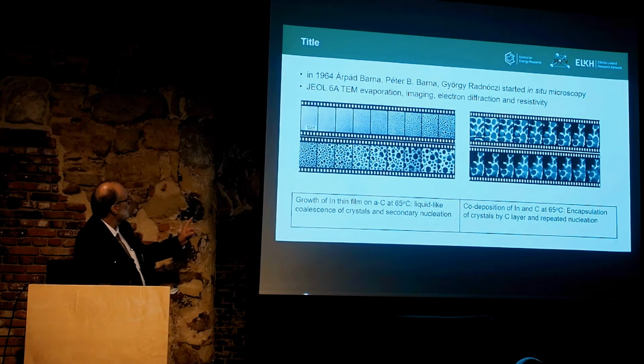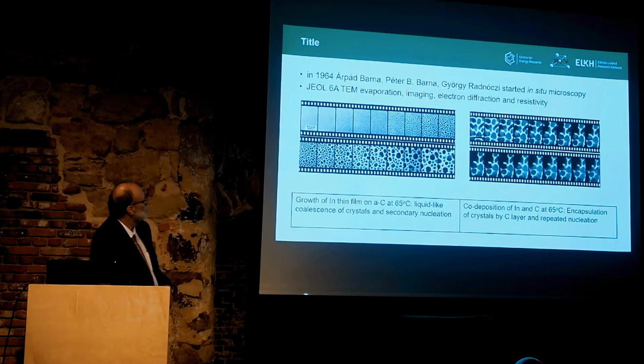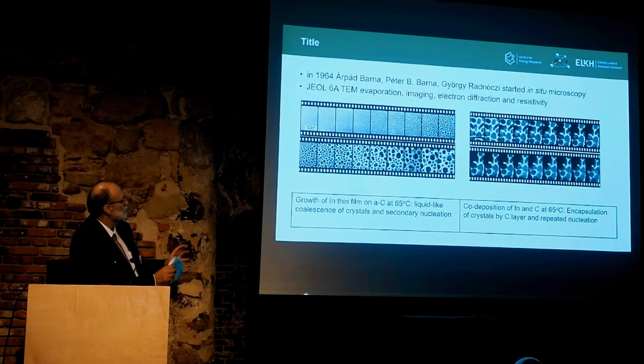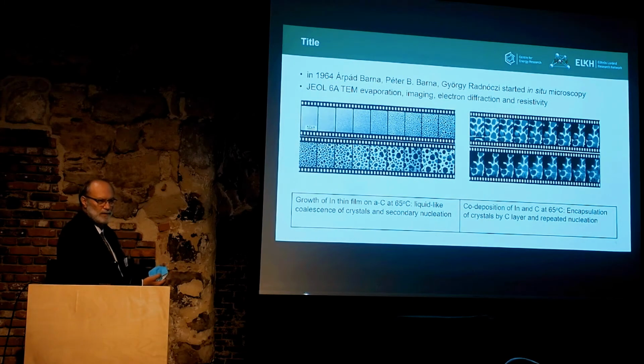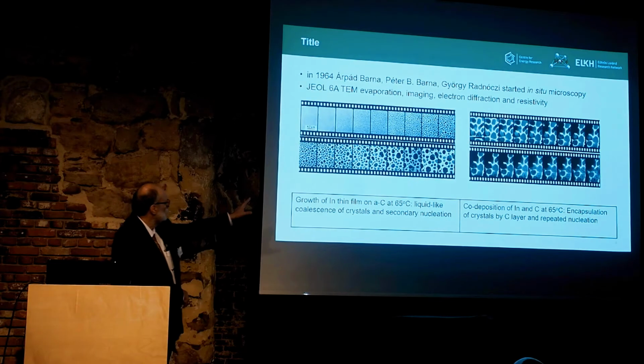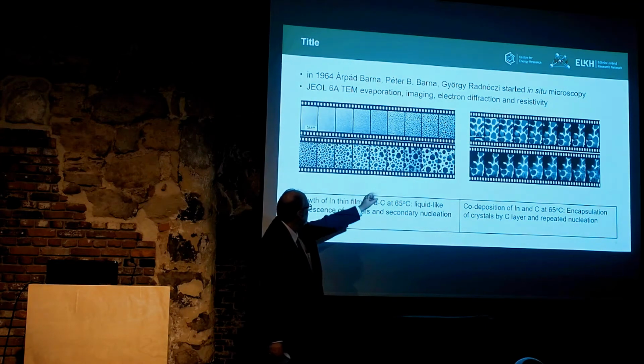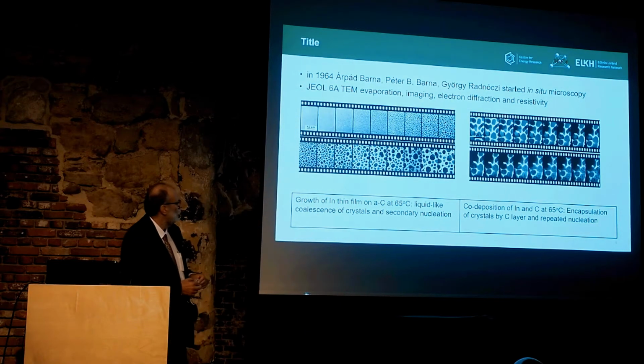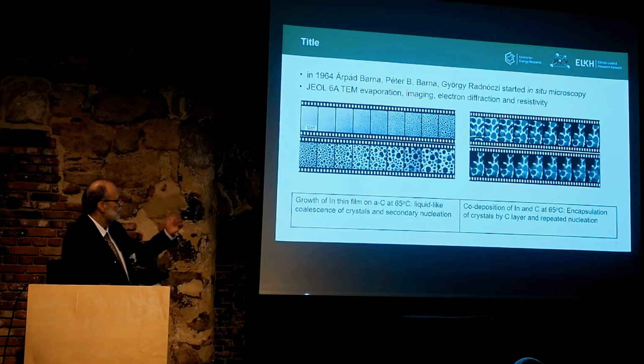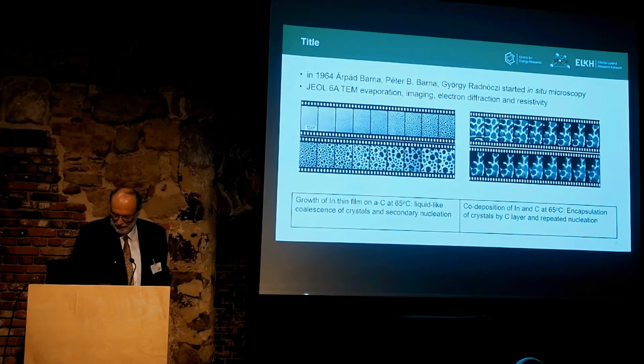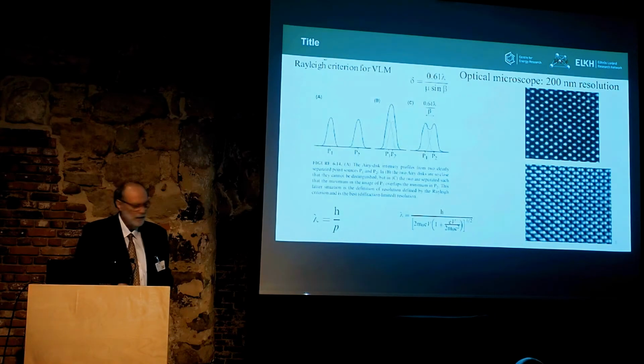So it was already in the 60s when these three colleagues, Árpád Barna, Péter B. Barna, and György Radnóczi, started not the microscopy, but in situ microscopy, which means that inside the transmission electron microscope, they not only imaged a specimen, but they started to evaporate material and took movies. And here the scale is already 0.2 micrometer, and you can see fine features. Actually, these are the images showing that the indium particles are growing, and some of them are observed in coalescence, and they could evaporate two different materials and study different material science problems with a better resolution than in an optical microscope.